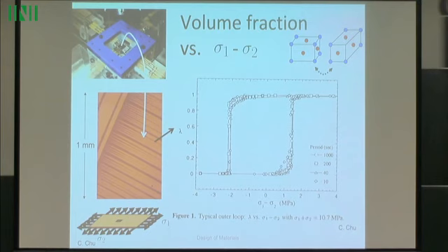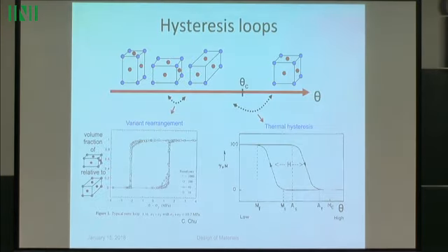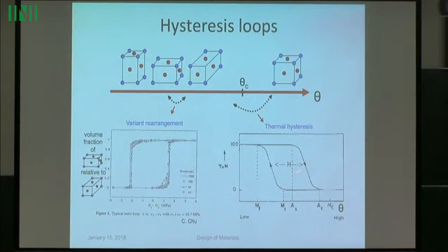So this is stress hysteresis. I could also have done a similar experiment with, in this case, thermal hysteresis. I would see a small rate effect there. And in fact, it's understood. It has to do with the fact of getting the latent heat in and out of the piece of material.